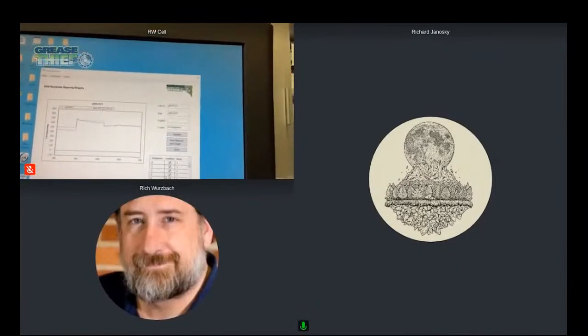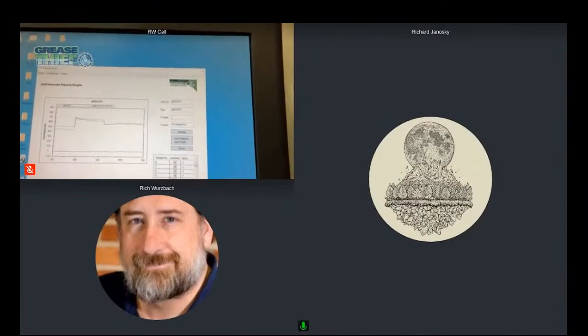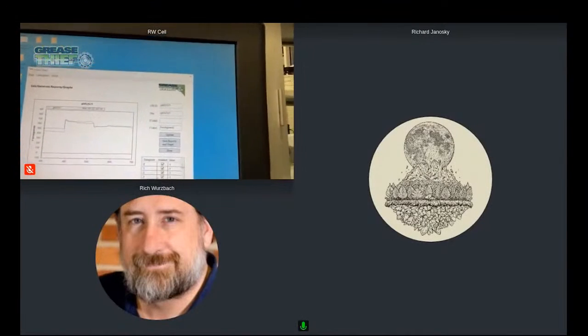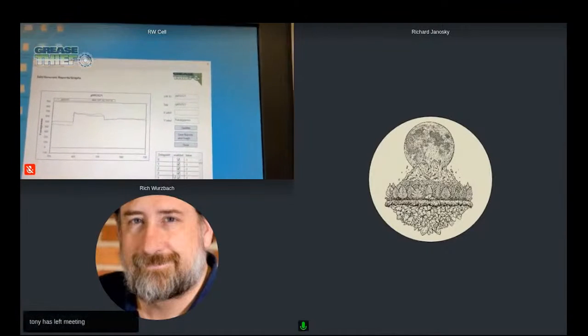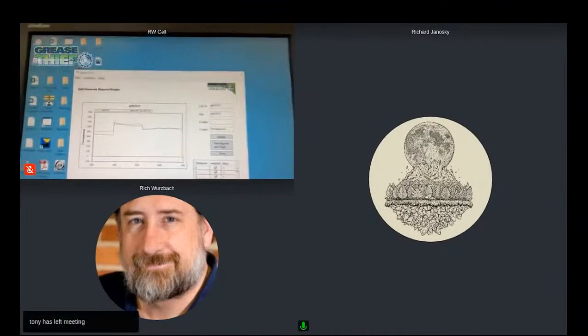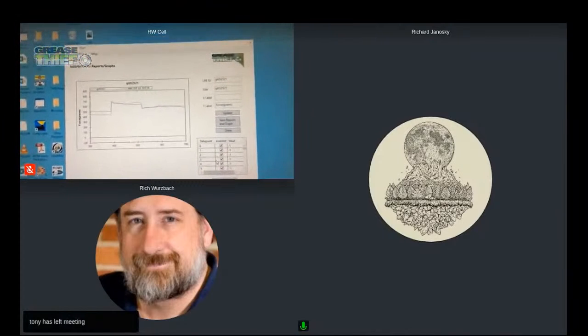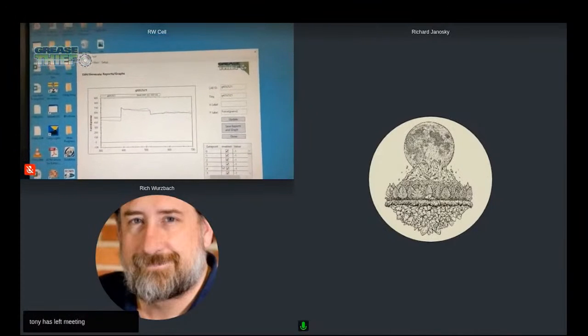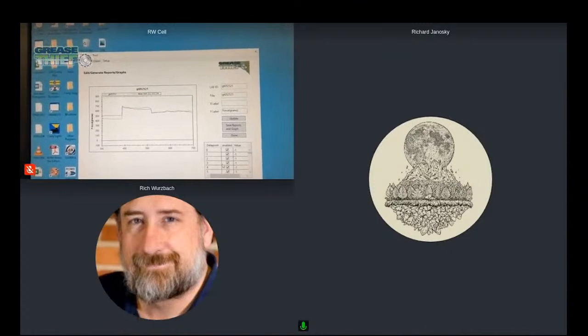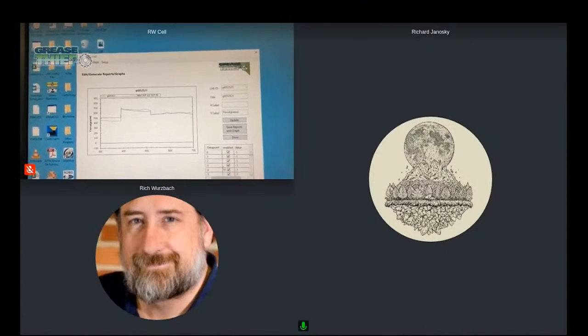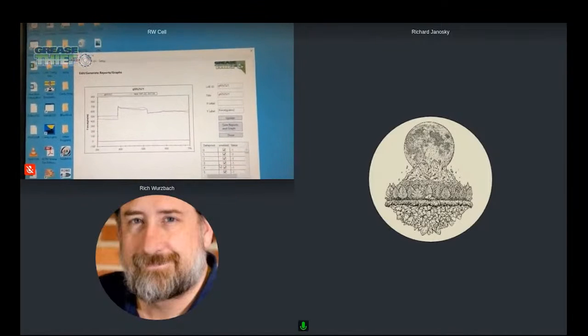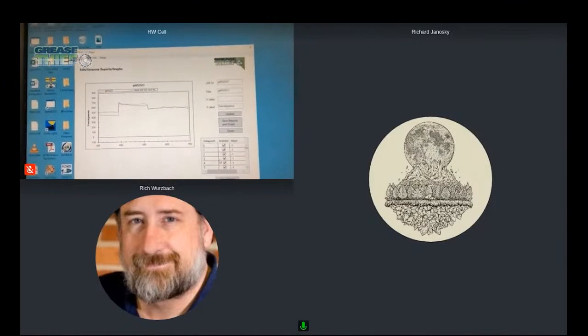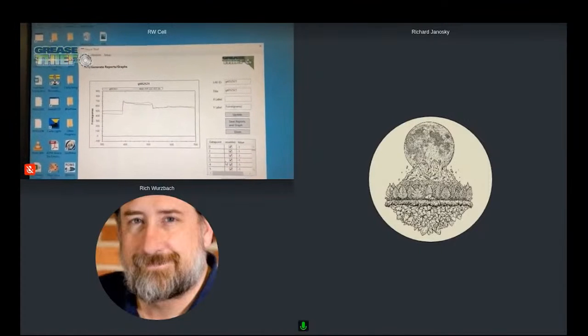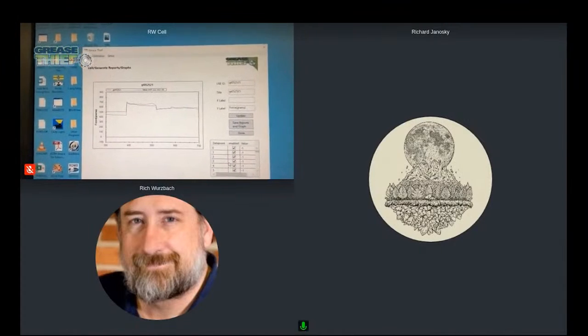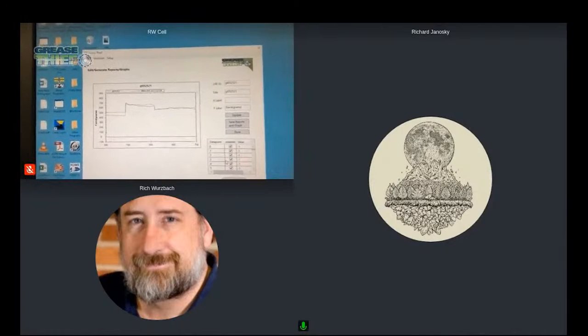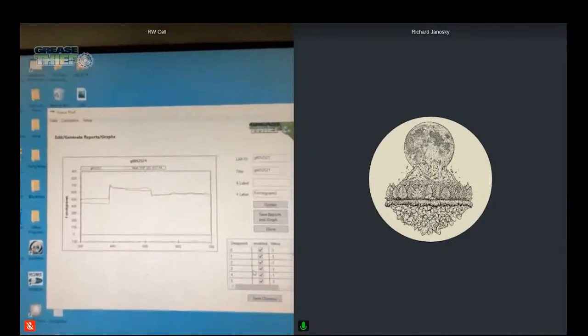So here we see this sample and baseline, and it might be hard to see, but that's because they're almost overlapping each other. So you have a red line and a blue line there, don't you? Yep. And we can see at the beginning that the baseline's the red line. It took a little less force to extrude. The sample took a little bit more. But then once it got into the higher speed and the medium speed, they're just about a perfect match to each other. So this GTI would be very, very close to 100.